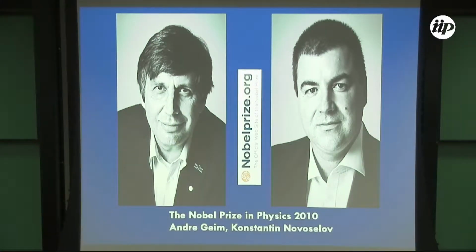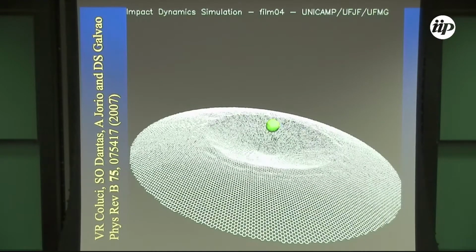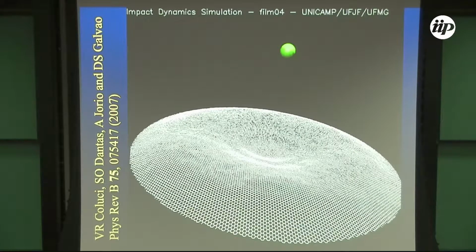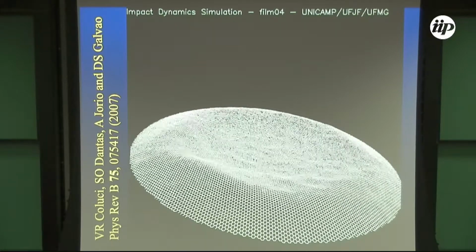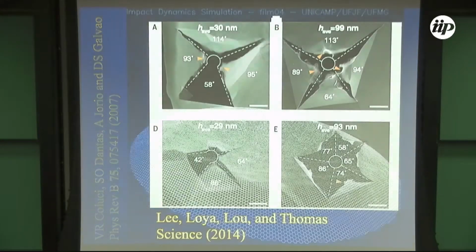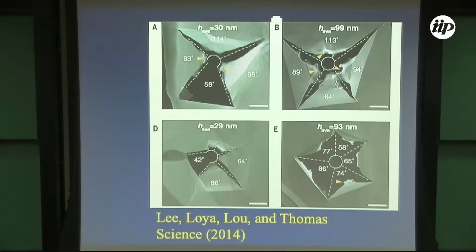With the advent of graphene, a real revolution started in materials science. But graphene has not only very unique electronic properties, it also has very unique mechanical properties. It's the ultimate membrane, just one atom thick. You cannot go below that. The fracture in graphene is also unique. Instead of breaking with the general shape of a ballistic projectile, graphene only breaks with very specific angles. These are called petal structures.